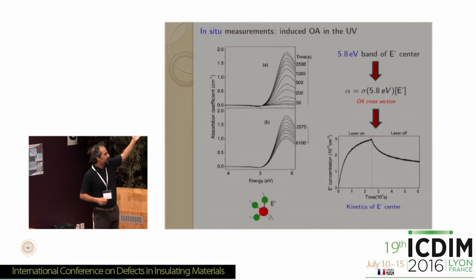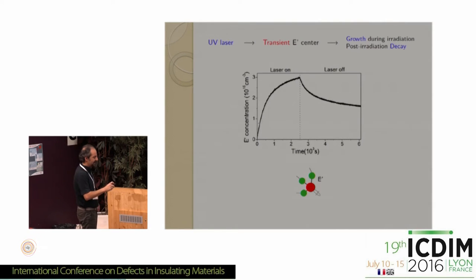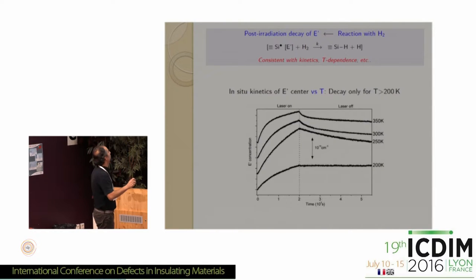So we found this setup informative in the sense that it allowed us to see the entire kinetics, and we began to study this in some detail. I'll tell you some of the results we obtained by this study. First of all, why does the center decay in the post-irradiation stage? What is the process responsible for this decay? Essentially, I'll jump to the conclusion: the process is the reaction of the defect with diffusing hydrogen present in the sample. There are several ways to become convinced of this, to prove this.